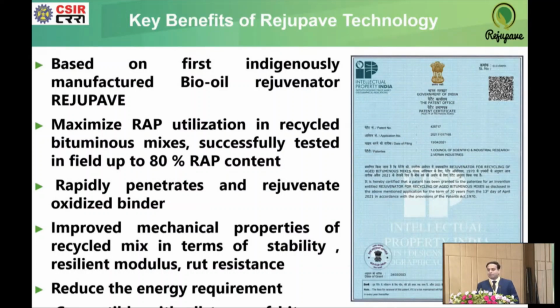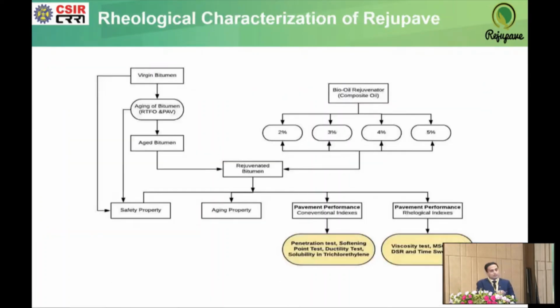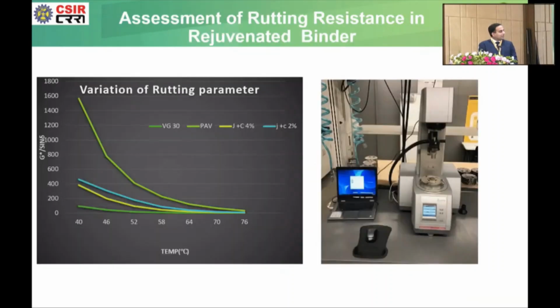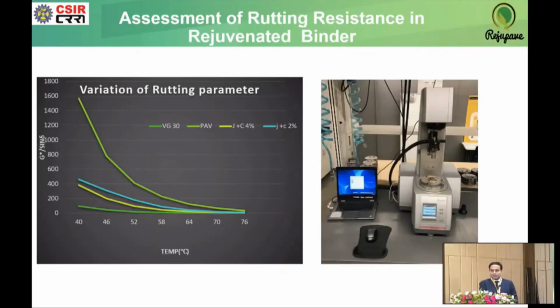Most of the rejuvenators in India are imported, but this is the first in India which has been developed through natural, renewable resources, and it's bio-oil based, therefore it is environmentally friendly too. Since the majority of rejuvenators are derived from petrochemical material, but this is completely bio-oil based, it facilitates high RAP utilization without altering the rheological properties of bituminous binder. We conducted extensive rheological tests during its developmental stage, which comprised dynamic shear rheometer analysis, pressure aging vessel, and all that. So it's a complete scientific study. We have published a couple of papers out of it, which you can find on Google regarding the technological aspects. Without going into the technological details, this is the dynamic shear rheometer test using Reju-Pave.